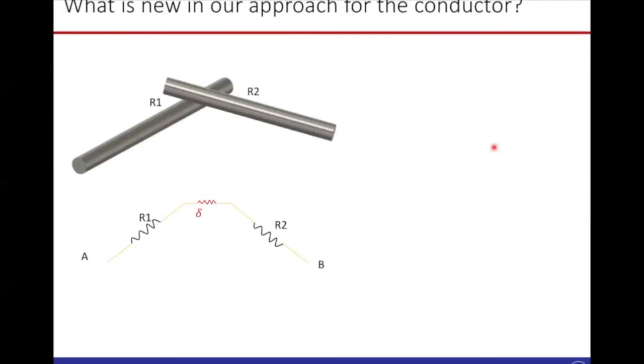Now we propose a quite different approach for this. Let's look at the approach we adopted to get a high conductivity. Consider two nanomaterials, say nanowires, having resistance R1 and resistance R2. Now we can represent this electrical network between these two points, A and B, as R1 + delta + R2. Here the delta indicates the contact resistance at the point where these two nanomaterials contact. So when you stretch this nanocomposite, the poor contact causes slippage, so the contact resistance can go high. And that's how the strain sensor behaves.